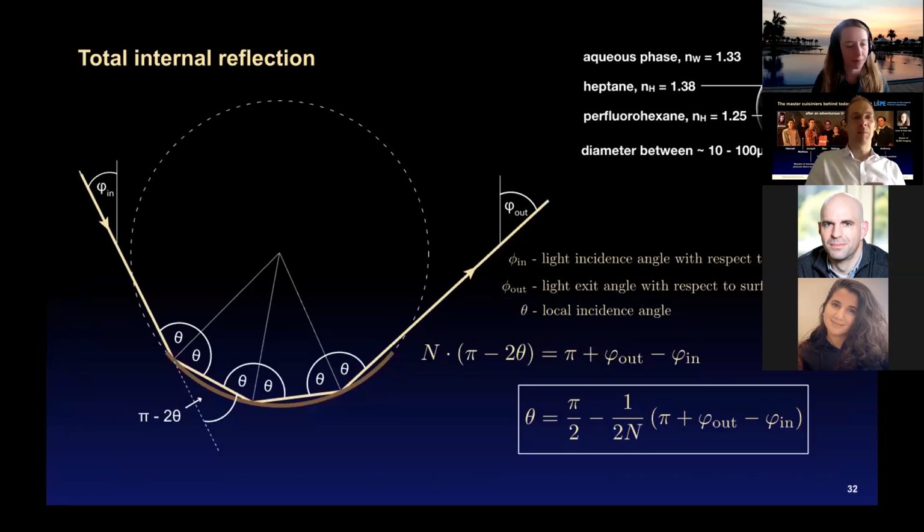The way the light has to propagate through there to create this edge effect is by total internal reflection. And so what I'm showing here in brown is this internal interface of the droplet, and a light ray coming in from the left and bouncing around this interface until it comes back out on the right, and then you can see it. So that was something we figured out pretty quickly. But total internal reflection doesn't tell you anything about how color could be changed, right? We're just redirecting light. We're not splitting it up, and we're not recombining it. And that's the key that I want to point out here: what's splitting, what's recombining here. And that took us a while to figure out.